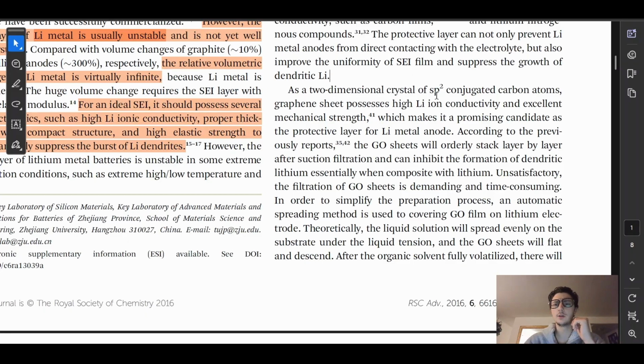As a two-dimensional crystal of sp2 conjugated carbon atoms, graphene sheet possesses high lithium ion conductivity and excellent mechanical strength, 41, which makes it a promising candidate as the protective layer of lithium metal anode. According to the previous reports, 35, 42, the graphene oxide sheets will orderly stack layer by layer after suction filtration and can inhibit the formation of dendritic lithium when composite with lithium. Unsatisfactorily, the filtration of graphene oxide sheets is demanding and time-consuming.